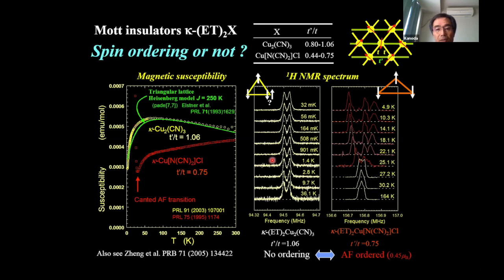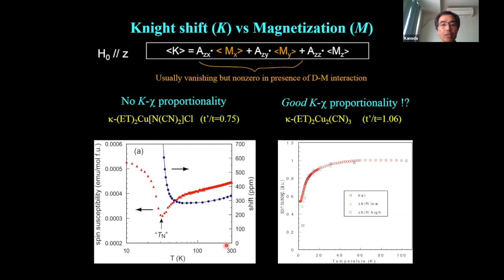Okay, but the triangular lattice does not show any change of the NMR spectra. This double peak comes from the nuclear dipole interaction, so it's not related to the electron spins. The important point is whether there is a change or not in the NMR spectra. So this material does not show any change in NMR spectra with temperature variations. And the spin susceptibility also shows no anomaly, just a very broad peak formation against temperature.